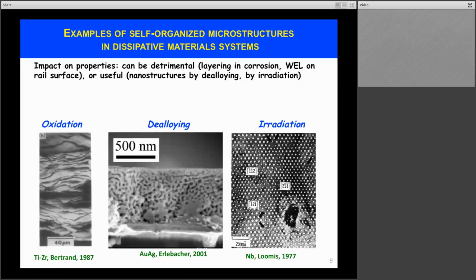This layering in corrosion is not good. It leads to a fairly fast oxidation rate by re-exposing the bare metal to the oxidizing environment. Another example is the well-known white etching layer on the surface of rails.